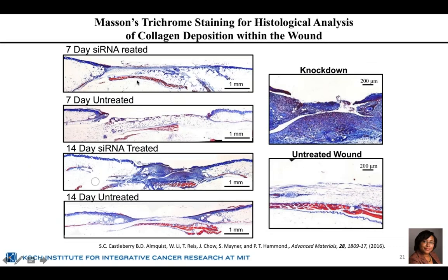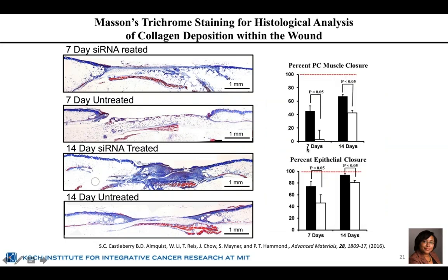And what we see in terms of wound healing is that after 7 days between the untreated and the treated, which is on the top, we see that the treated sample has a narrow bridge of collagen, which is stained in blue here. After 14 days, we see that that narrow bridge has become a large sort of chunk of tissue that has been deposited in comparison to the untreated wound. So we can see also effective increases in the rates of wound closure in these animals, both with the panniculus carnosus muscle and the epithelial closure.